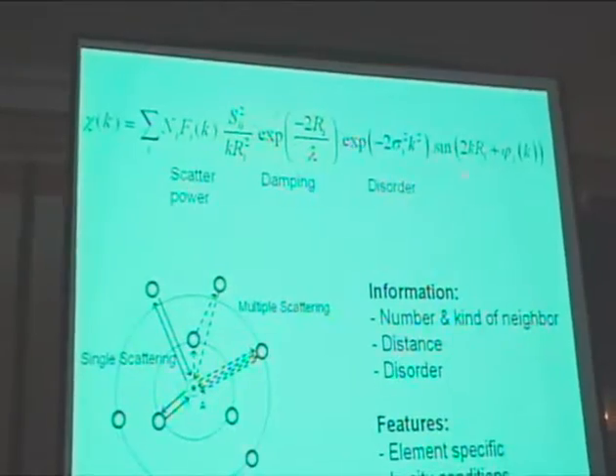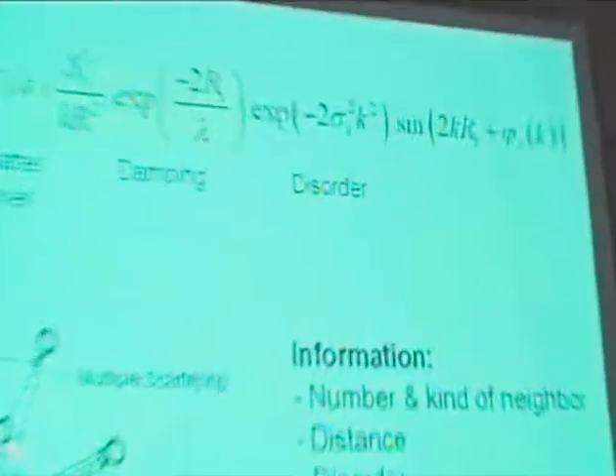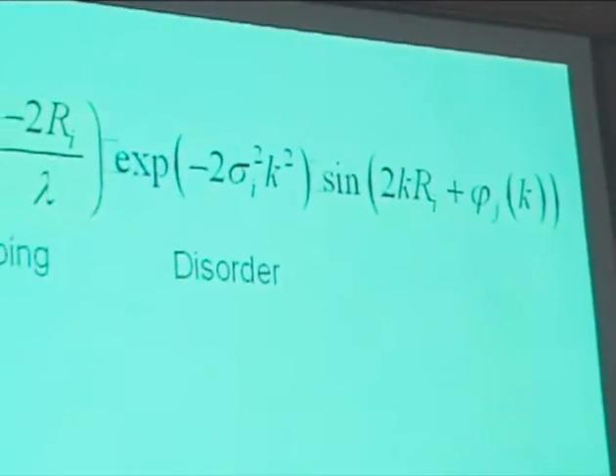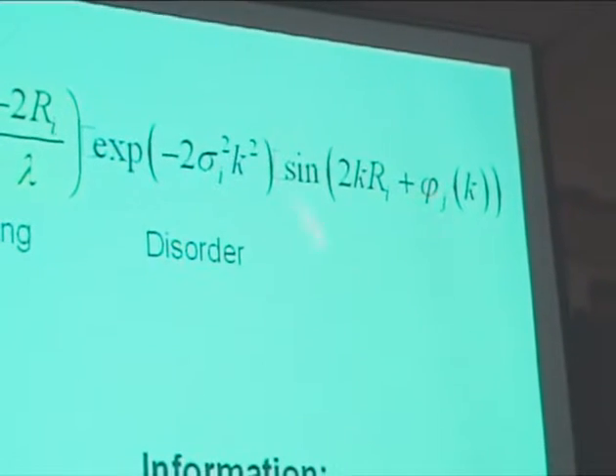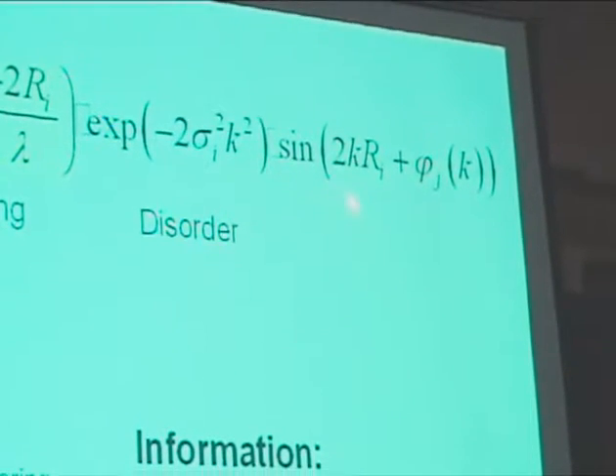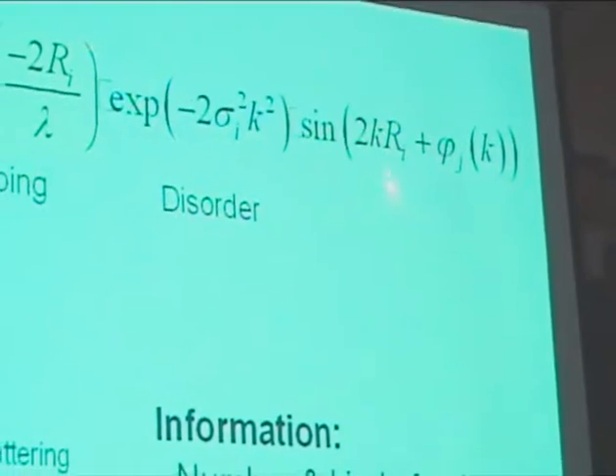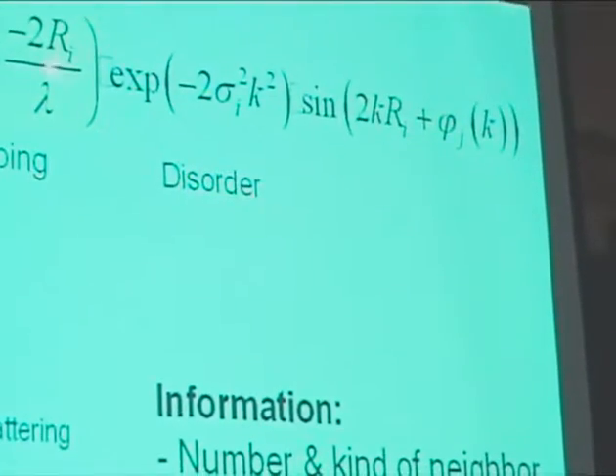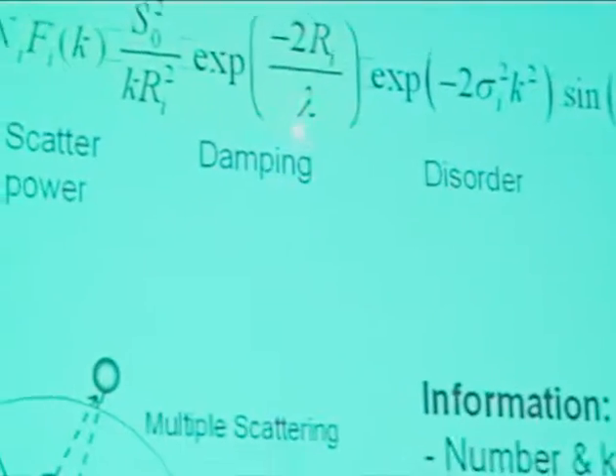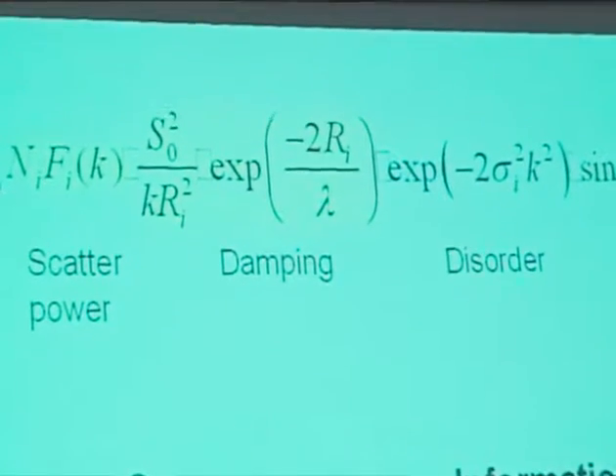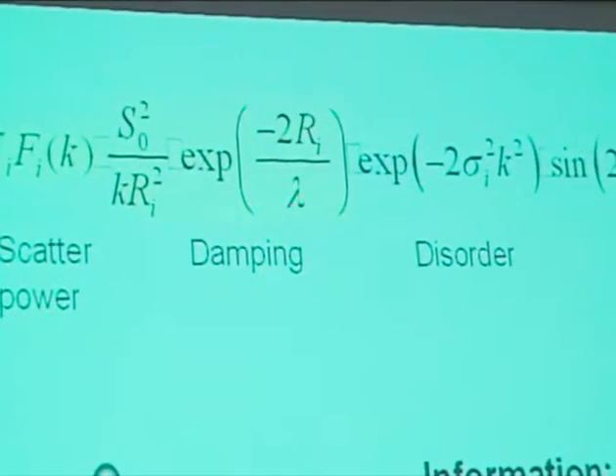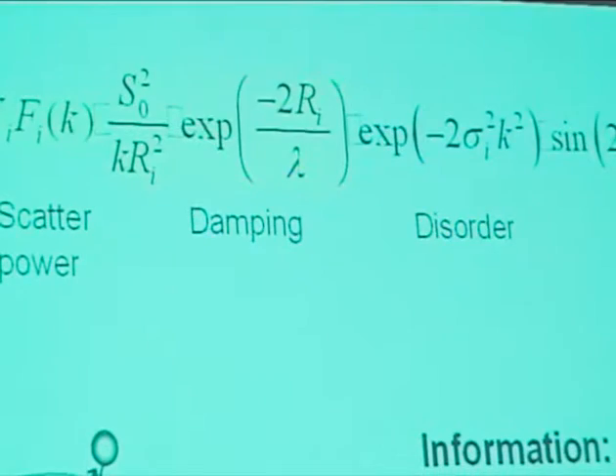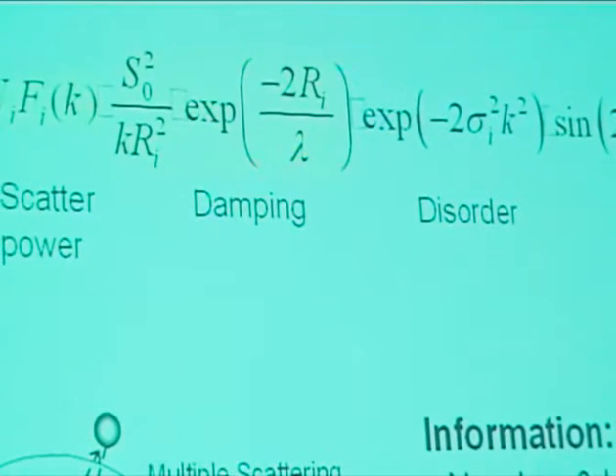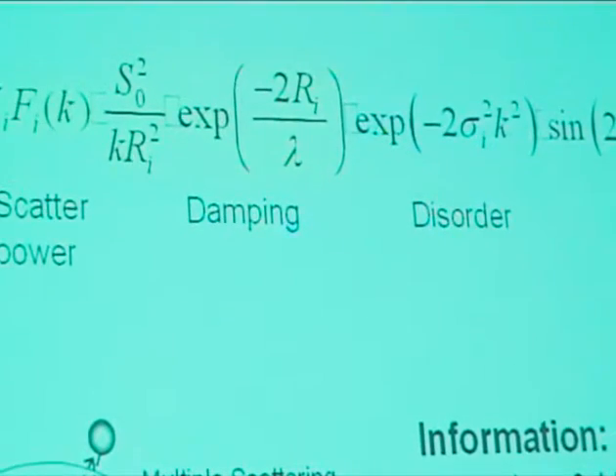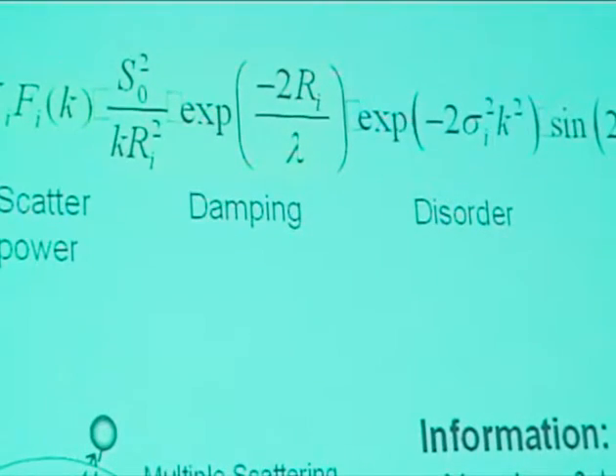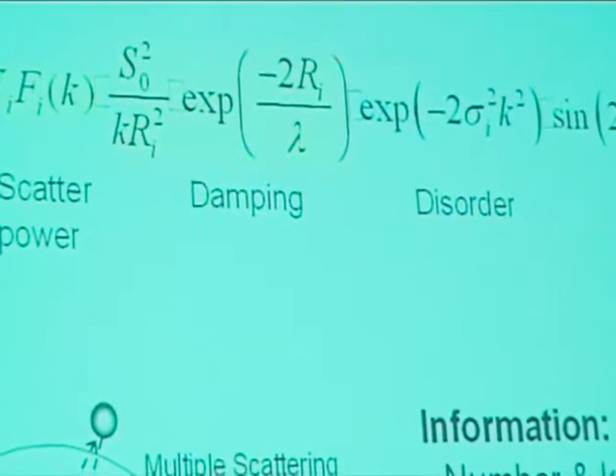First of all, you have a sine type of argument, which is because of the outgoing and back-going wave. So it's an interference effect. It's either a sine or a cosine or an exponential, whatever way you want to write it. And then there is a damping effect, like in XPS, because the electron goes out and is eventually scattered so many times that it loses its information, there is no information left. Because of this damping effect, you can't see much more than a few shells surrounding the original atom.